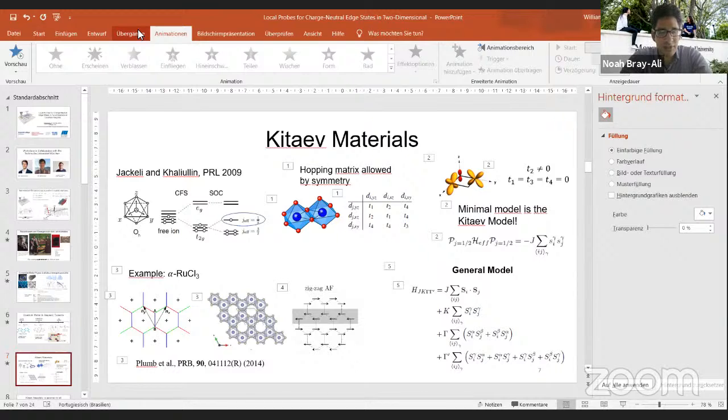And I wonder if you thought at all about the iridates in the context of your calculations for doing tunneling to measure the structure factor. Just as a note, we looked at the 214 iridate that has a similar setup, but it's corner-sharing octahedra. It's a Mott insulator with Heisenberg dominating. And we saw some mid-gap states, because the main thing you see is the Mott gap. But we saw these mid-gap states that we interpreted in exactly the way that your calculation interprets that. You see it as a step at the Heisenberg coupling. You call it, in the Kitaev case, the vison gap.